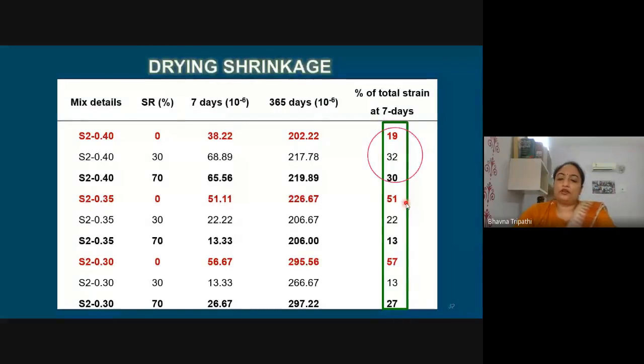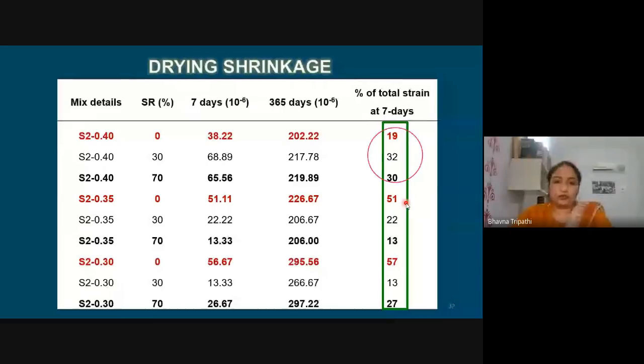So overall, what do we conclude from this is that as far as shrinkage strain and the dimensional stability of concrete are concerned, we can get a very promising, very beneficial effect of adding ISF slag. Why am I saying this? It is clearly evident that addition of ISF slag in larger quantities reduces shrinkage strain initially, and whatever the shrinkage is, it is very gradual. It is not sudden, it is not rapid, which is very beneficial when we talk about creep.